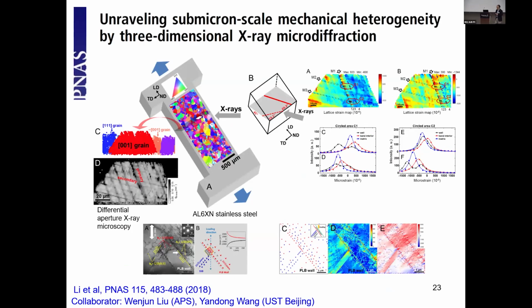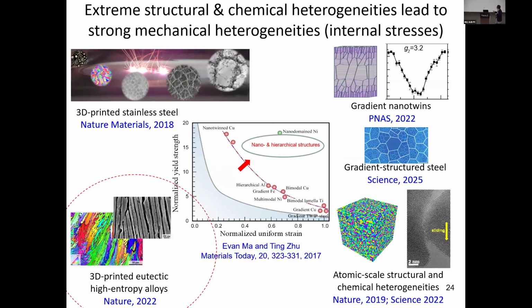We are not satisfied with just this prediction of the mechanical behavior at the sample level. We also used this spatially resolved X-ray microdiffraction at APS to measure the lattice strains within the grains. You can see the dark and light gray regions represent the hard and the soft regions. So we have the spatially resolved lattice strain measurement to map out the lattice strain or the internal stress distribution within grains. This enables us to understand the spatial and temporal evolution of internal stresses.